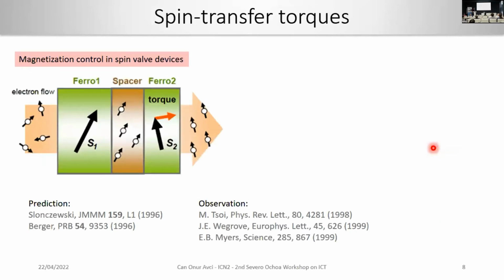So let's talk about the earlier concept. The spin current was initially obtained by passing a charge current through a ferromagnetic layer. If you make a device like this, where you have one ferromagnet that acts like a spin source, and you put a spacer in between with a second ferromagnet, then the spin polarization of the conduction electrons going through the first ferromagnet can act as a torque on the second ferromagnet. Therefore, you can control the magnetization state of the second layer, which I'm going to call the free layer, because that's the one that you want to switch or manipulate, and this will be your fixed layer. So you can engineer these materials to bring some spin angular momentum from the first layer to the second layer and switch it.